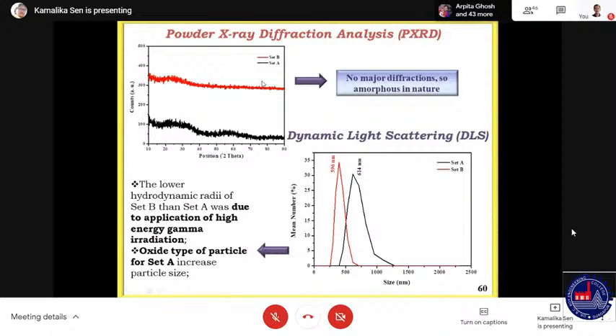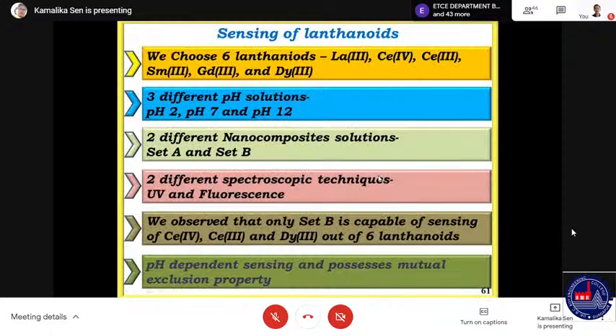In the powder XRD, we can see this is also amorphous, as there are no peaks in the powder XRD pattern. And the dynamic light scattering experiment shows higher diameter, although the trend is the same. That means the irradiated particle is lower in dimension than the non-irradiated one.